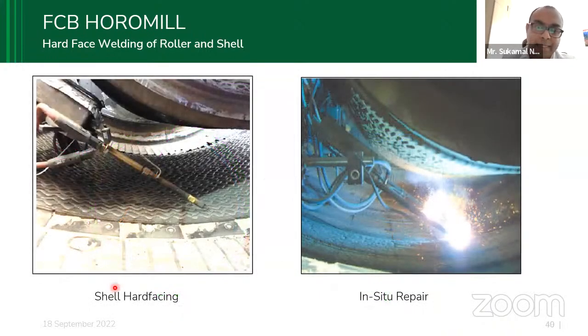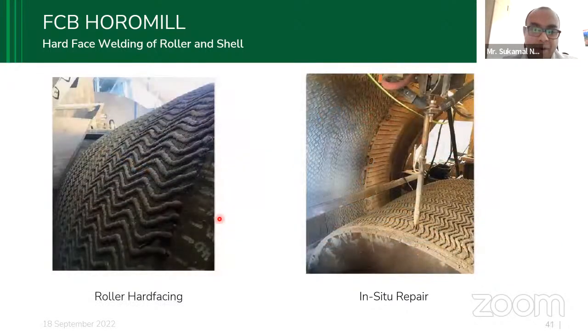This is shell hard facing we are doing here. You can see this is a long torch we use, and then there's a method, and we do in situ repair in the cement plants. Practically we always get a maximum 7 days shutdown, so we have to finish everything in 7 days. So we can understand how efficiently we have to do it. And for the next 1 year, the cement owners don't want any unwanted stoppage of their production. This is how it looks after welding. You can see here.